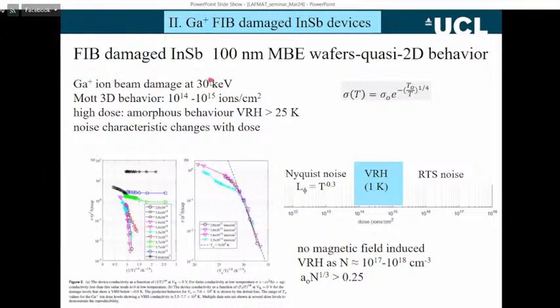What we find is, if we measure the conductance in the disordered region, it goes over to this Mott variable range hopping. So with introducing this disorder, we can go over to this situation where we have this hopping behavior, and the device conductance follows this exponential behavior now with a kind of a mobility gap, but with a quarter power there. Okay, if we look at the actual experimental data, on the left here we have device conductance. Again, it's on a log scale because we've got changes over orders of magnitude of conductance as a function of 1 over T to the quarter.